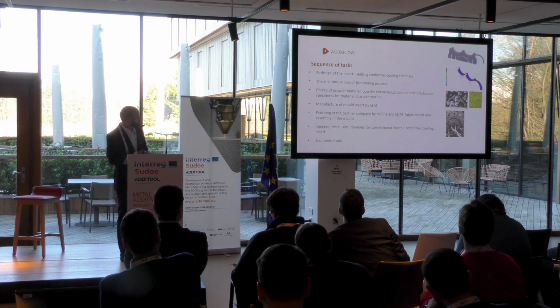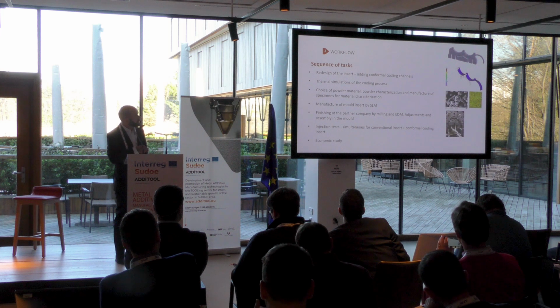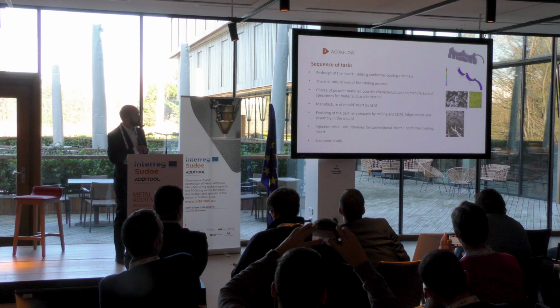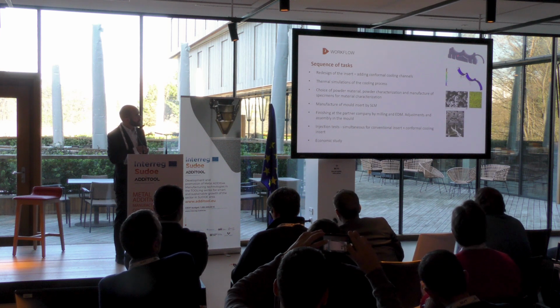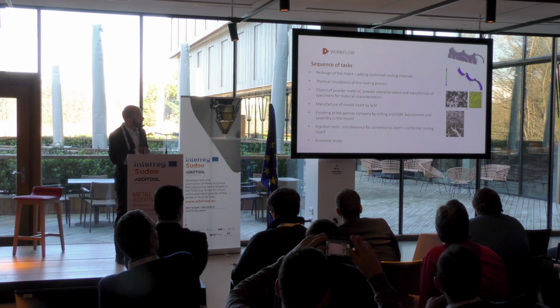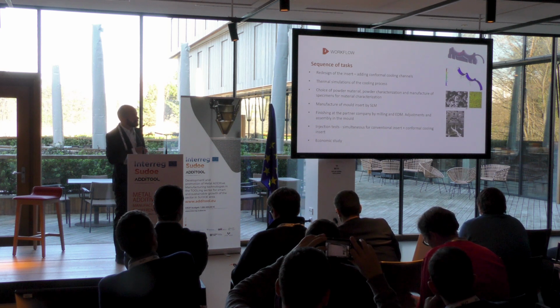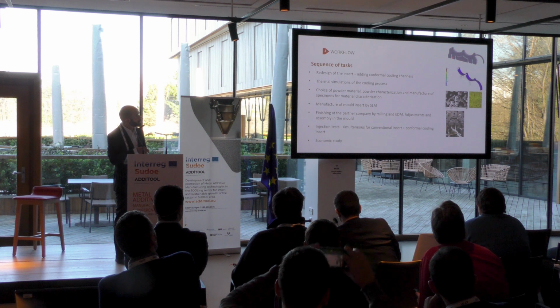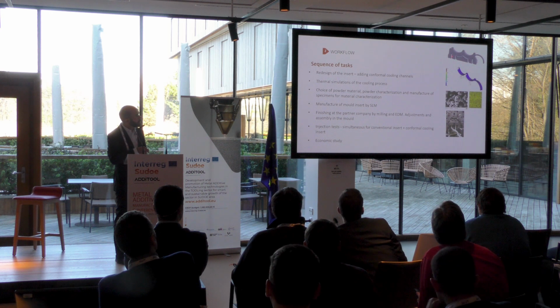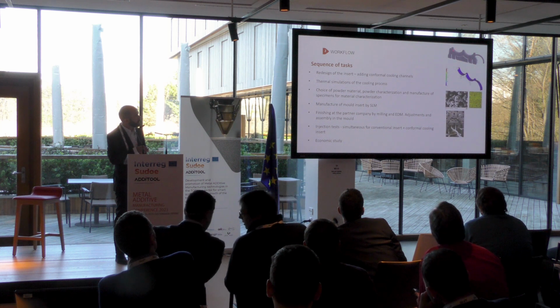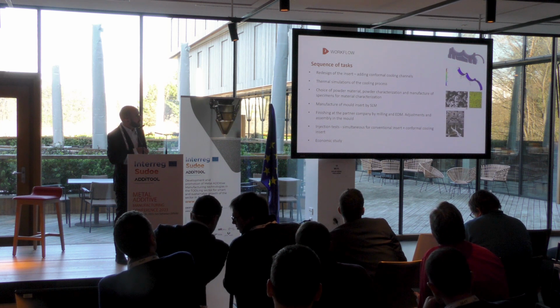So the first task was to redesign the existing inserts, adding internal cooling channels which weren't there in the first place. This is actually not the final geometry of the insert, because these channels were switched and optimized. They now more closely follow the contour of the molding area.